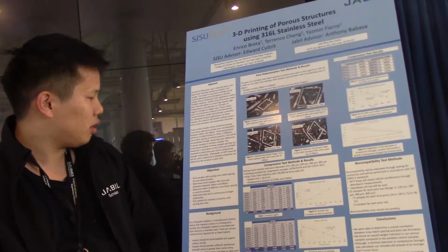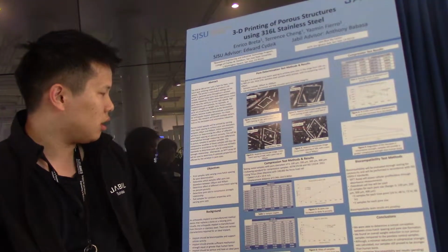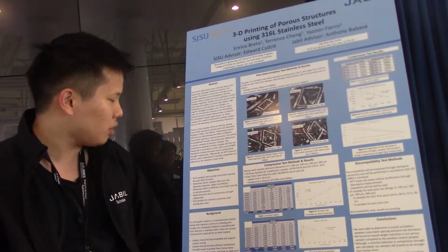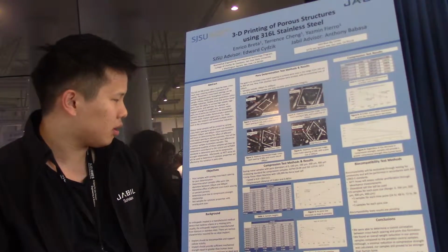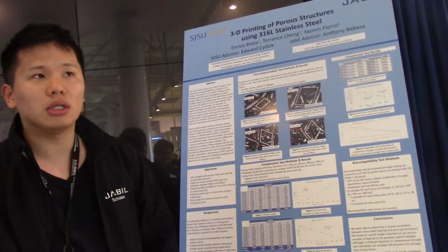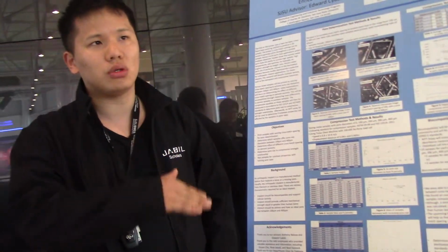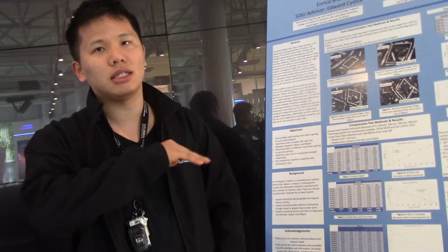Now, in terms of the actual results, we were able to confirm that the porosity increases in a consistent manner as you increase the pore size, which seems to indicate that we could control for a certain pore size within the sample.